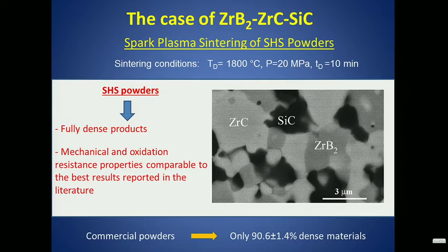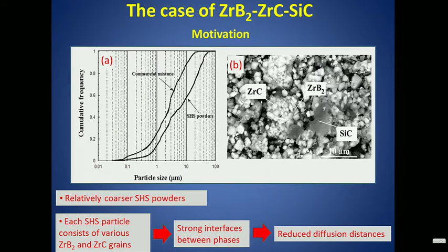If you process them by SPS, you get a microstructure of this type, and you get a fully dense product, with mechanical properties that are really very much comparable to the best results reported in the literature. If you compare the sinterability of these powders we have been producing with the commercial powders, there is no match, because you can get only 90% relative density. So what is the reason for that? Even if our SHS powders are coarser with respect to the commercial mixture, each SHS particle consists of various grains of boride and carbide, so there are very strong interfaces and the diffusion distances are reduced during the sintering. That's the reason why we get better results.